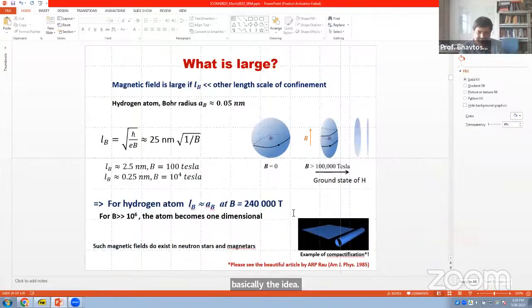So when we talk about large magnetic fields, or for the magnetic field to have a substantial perturbation on the state of the electrons, you would expect this to happen only if the cyclotron radius is much smaller than, or at least comparable to, the other characteristic length scale in the problem, which in this context is the Bohr radius, as I discussed. It turns out that for a free hydrogen atom, this is a very, very large number, something like 240,000 Tesla.